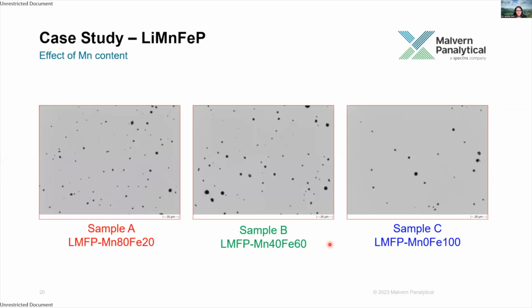So now let's look at an example of a series of cathode materials which were measured on the Morphologi 4. So here we have three lithium manganese iron phosphate cathode materials, and these had differing ratios of manganese to iron. On the left, we have an 80-20, in the middle, we have 40-60, and then on the right, we have just iron phosphate. So the purpose of this study was to understand the impact of the manganese on the particle size and shape, and then take this back to powder properties.